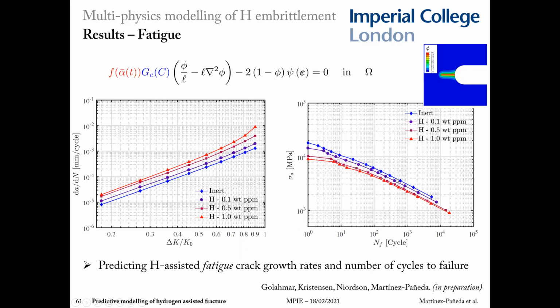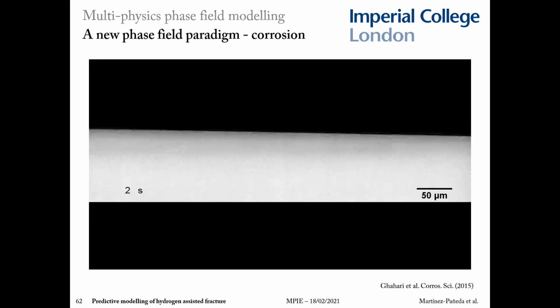And I emphasize here that the Paris law behavior and the SN curves are an output of the calculation, they are a prediction basically, not an input, because this is quite different from other existing models. And I'm going to end this talk just by showing very briefly another exciting avenue of research, which is the use of phase field modeling to capture how the surface of a corroding metal evolves.